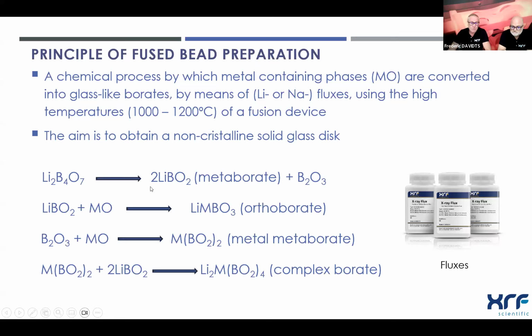So lithium tetraborate will be divided into two different chemicals, and those chemicals will react with our metal-containing phases, so the elements that we do want to analyze. And at the end, we will get a complex borate that has the same form for all the phases. So do you remember the clinker where we had 5 different calcium phases? Well, when we are using the fused bead method, all the calcium phases will have the same borate complex.